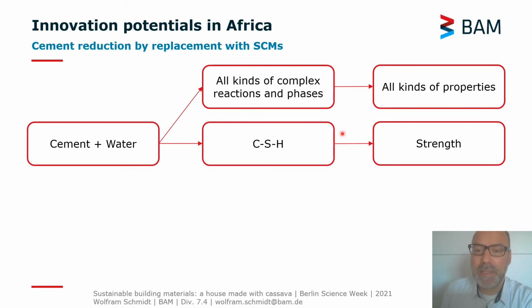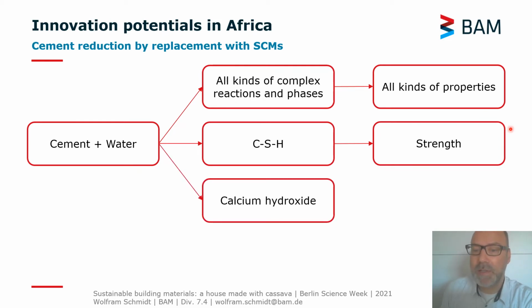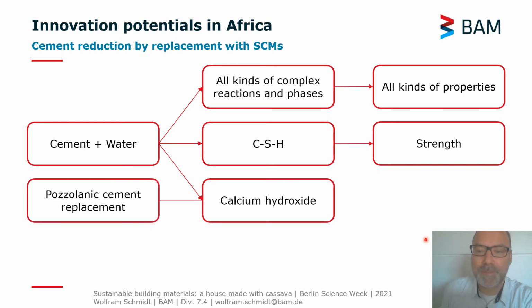But the most important phase is the reaction of the calcium silicate hydrate phases, because these calcium silicate hydrate phases provide strength to concrete. And closely linked to it is the formation of calcium hydroxide, which provides certain properties in concrete, but mainly does not contribute to the strength of concrete eventually. And this is the point where the supplementary cementitious materials, particularly the pozzolanic materials, come into the game, because these pozzolanic materials react in a secondary reaction with the calcium hydroxide.